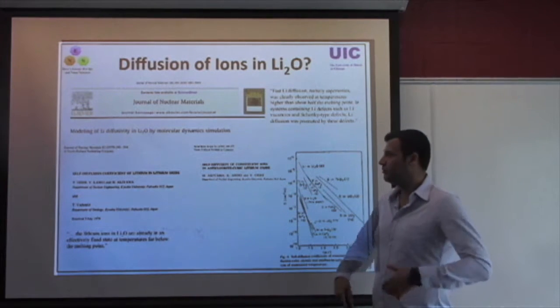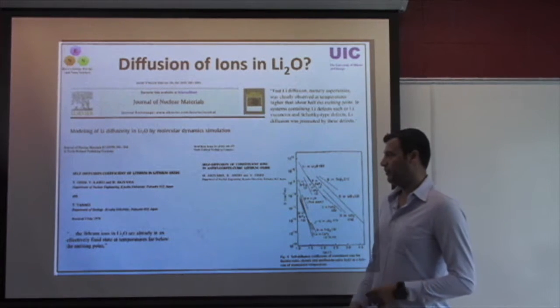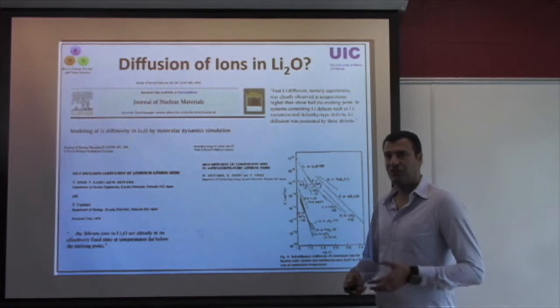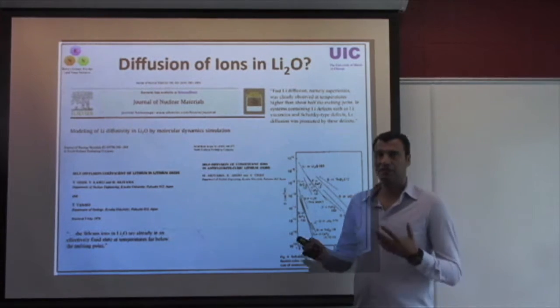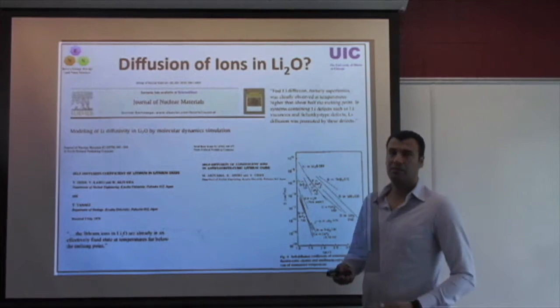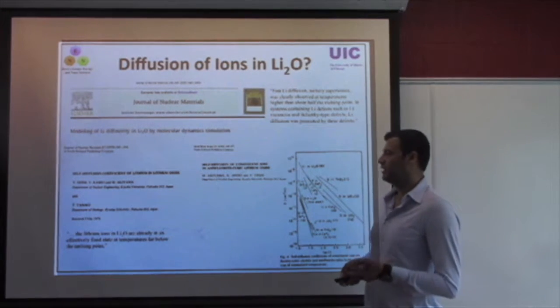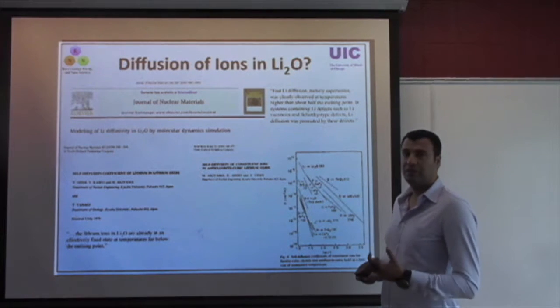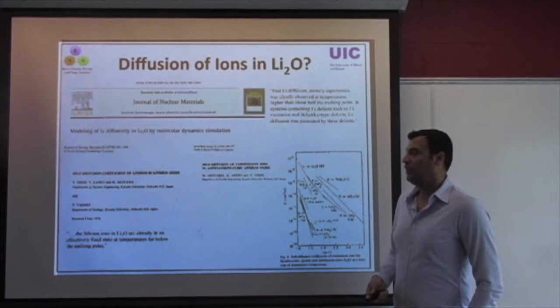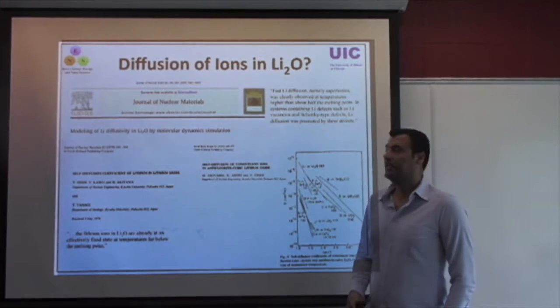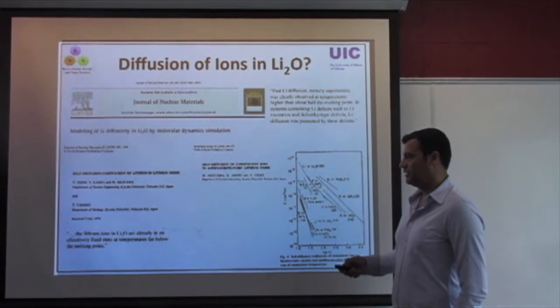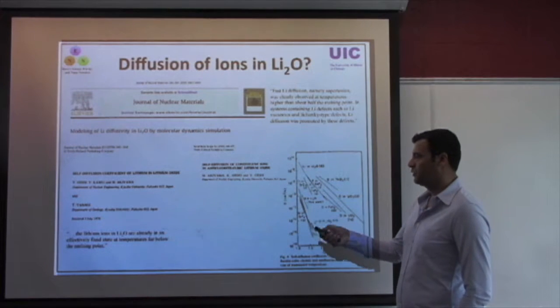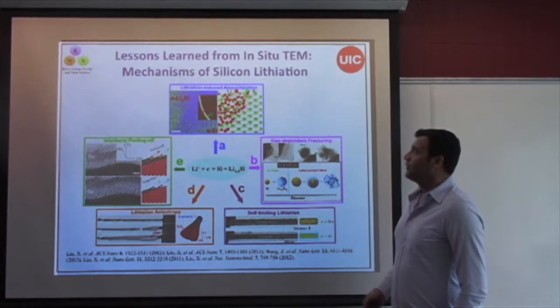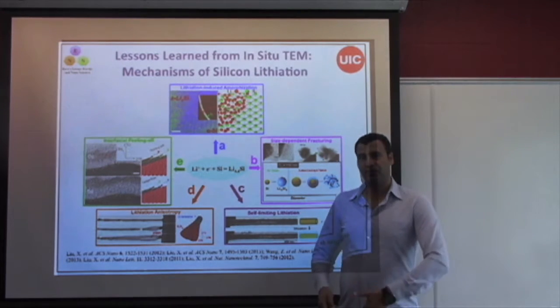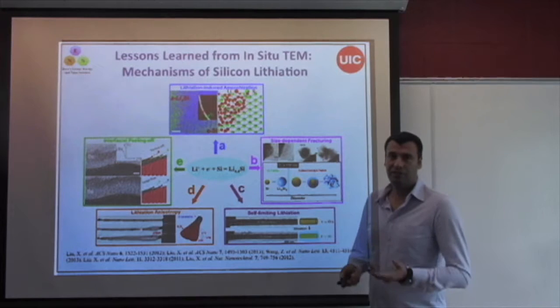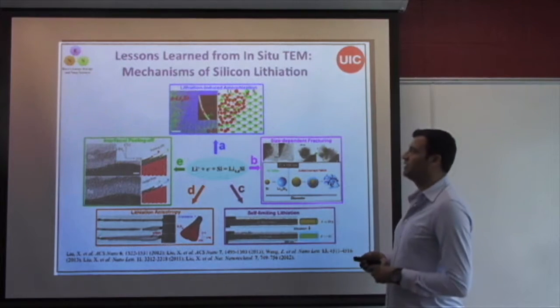That can also happen for sodium, but if you are dealing with some multivalent systems, for example magnesium, if you try to do the same thing and look into magnesium transport through MgO, magnesium oxide, then you see that the kinetics and the dynamics of reactions significantly slow down, and there could be some interesting research conducted to better understand how multivalent ions could transport within the oxides. So I will give you some summary of what is new we understood by doing in situ TEM on various electrodes and materials.